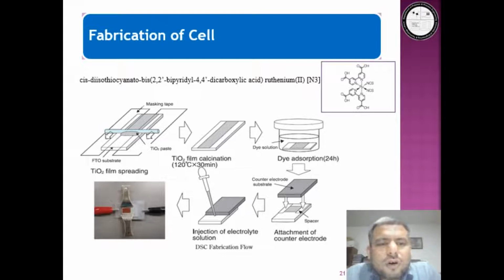Now, how to fabricate the solar cells? The first step is that titanium coated glass was heated at 450 centigrade for 30 minutes. Then the coated substrates were dipped in a 0.5 millimolar dye solution for 24 hours. After complete sensitization, the photoanodes were washed with methanol to remove the free dye. Similarly, as you see in the figure, platinum coated substrates were annealed at 450 centigrade for 50 minutes to make the